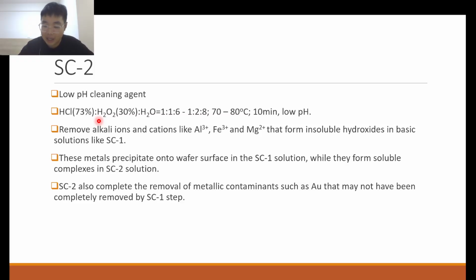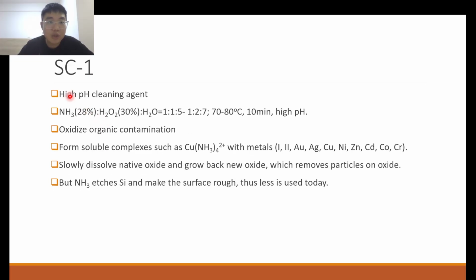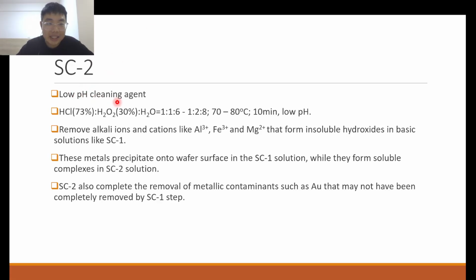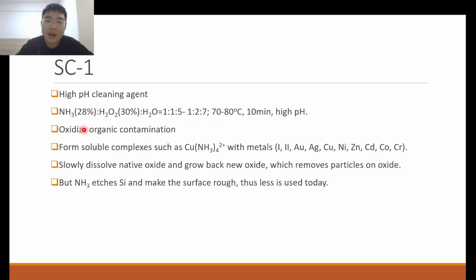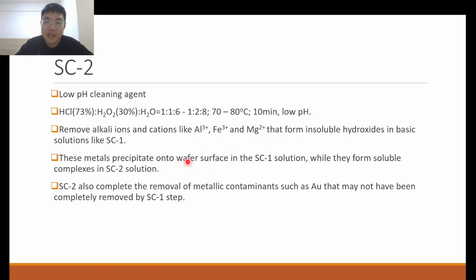Okay, and so if you have SC1, turns out we also have SC2. SC2, in contrast, is a low pH cleaning agent. SC1 is alkaline, SC2 is acidic, and so we still have hydrogen peroxide dissolved in water, but now we use hydrochloric acid instead of ammonia. What it does is that it removes alkali ions and certain cations that form insoluble hydroxides in basic solutions like SC1. Remember in SC1, your ammonia is able to form soluble complexes with certain metal ions, like copper, zinc, silver and gold. However, certain metals, for example Mg, Fe3+, Al3+, form an insoluble metal hydroxide in ammonia solution.